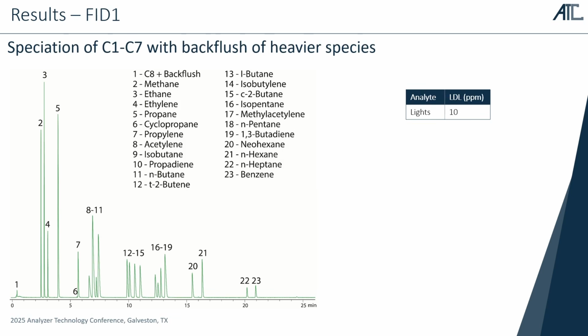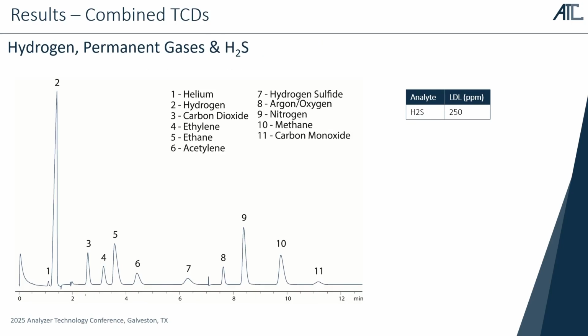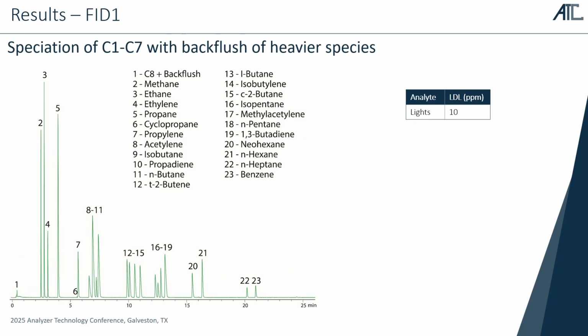We have really sharp Gaussian peaks, allowing for us to see the separation, as you can see in peak groups 8 through 11, with our acetylene, our isobutane, propadiene, and normal butane. We're getting good separation and good resolution. If we were on the packed columns, by the time these are coming out, it's harder because they're wider peaks to keep them resolved and keep good quantification on them. This chromatogram goes all the way out through our benzene with speciation across with the olefins and the alkanes.